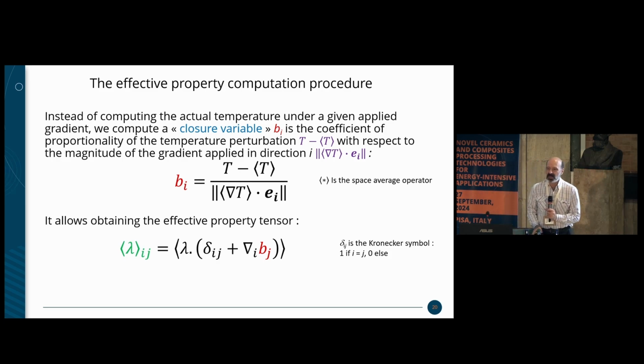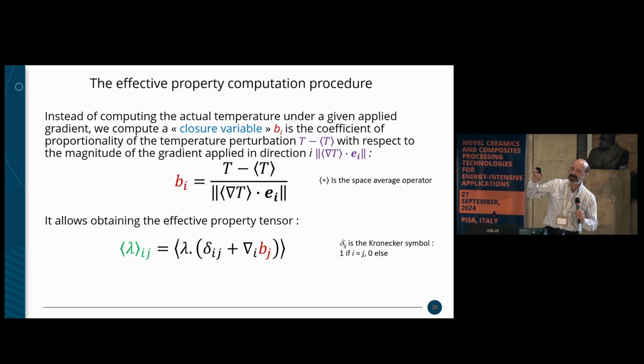Then, computing the effective property computation. I'm sorry for the formulae. The idea is that you don't want to compute the actual temperature under a given applied gradient in a given small bit of the material, because you would have to repeat that forever in many situations. So to be more general, you take what's called a closure variable, which is the proportionality between the temperature perturbation, which is actually the difference between the actual temperature and the average temperature, compared to the magnitude of the average thermal gradient applied to the material. If you got a strong average gradient, then you have strong perturbations. If you have a small average gradient, then your perturbation is small, okay?